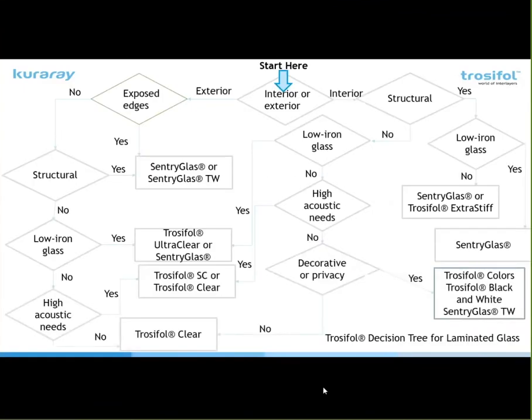If it's structural and outside, we still recommend Sentry Glass. If you're inside and it's structural and it's not low iron glass, then a Trosifol extra stiff, a stiff PVB, is okay. Stiff PVB has its stiffness properties up to 30 degrees C or 86 degrees Fahrenheit. So that's why we say if it's an interior application, it's okay, but we wouldn't recommend it for outside. And you can see how you would go through this decision tree to come up with the selection for an interlayer. If you have any questions, obviously you can contact us and we can help you with that.